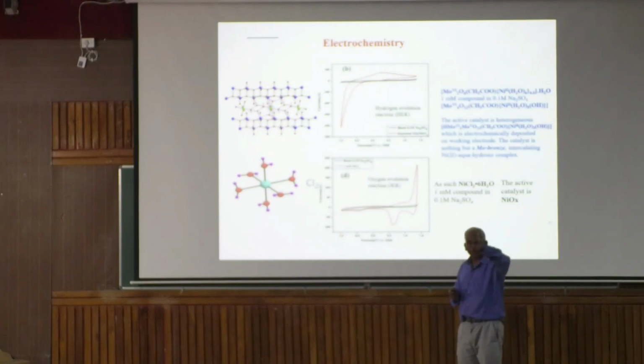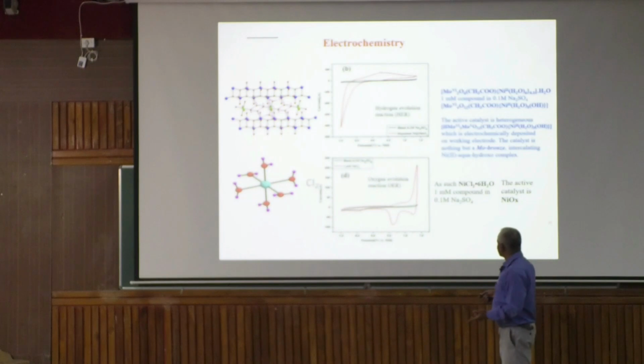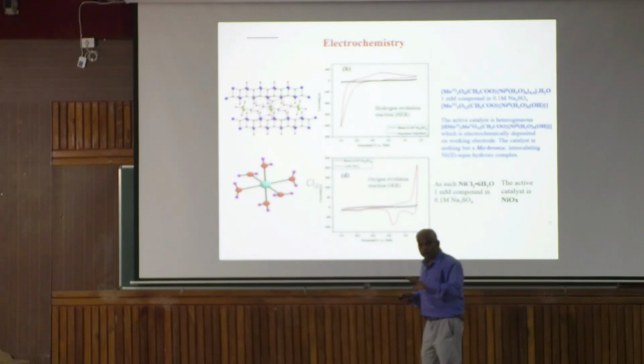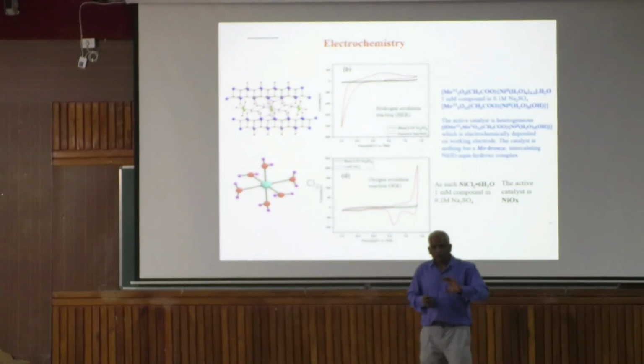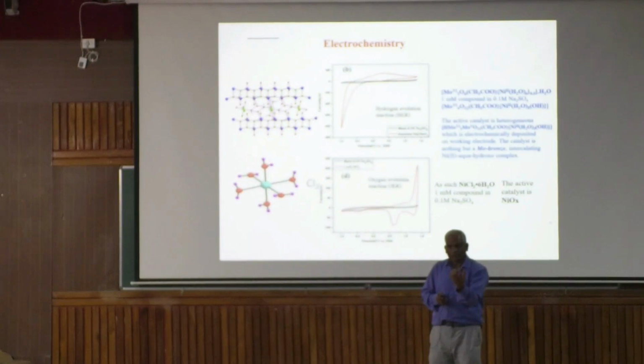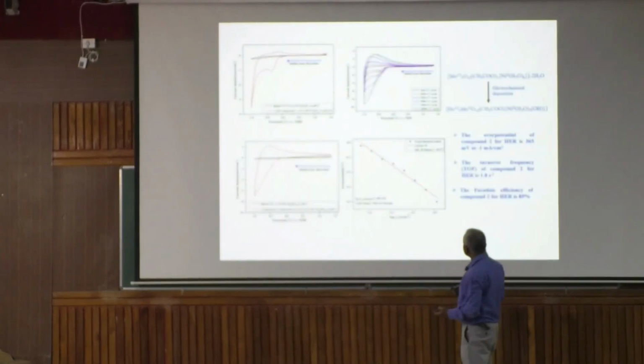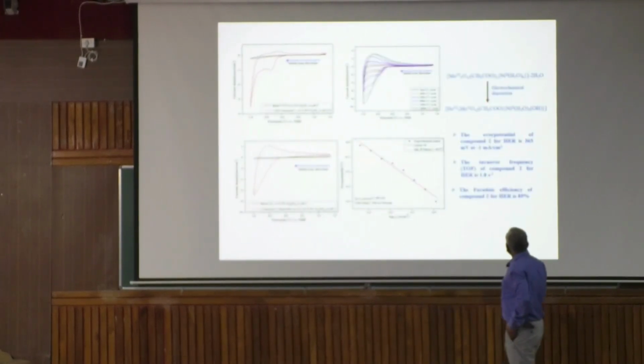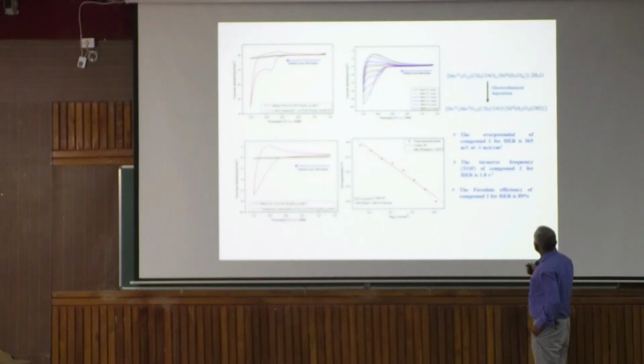So nickel 2 went to nickel 1, and nickel 1 reduced the proton to hydrogen. But let me tell you, it is not homogeneous. We started with homogeneous, but slowly some electrodeposition happens on the electrode. What is that compound? That compound we characterize now. So this is the compound originally in aqueous solution. Now this is the deposited compound we characterize, and this is actually the catalyst that gives the hydrogen evolution.